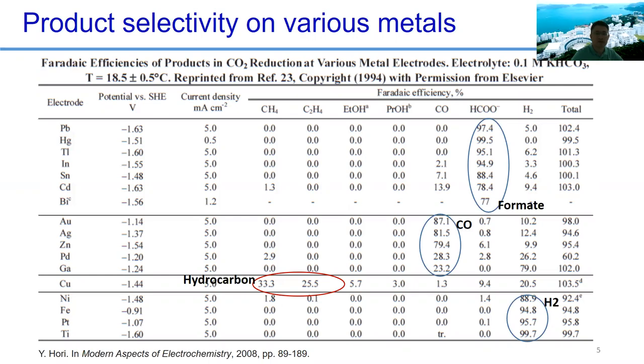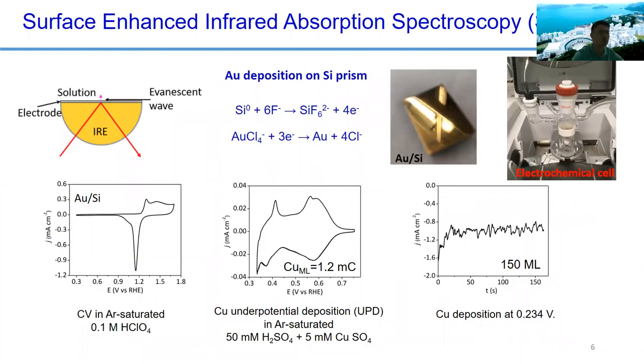And you can see that copper is very special. It's the only surface that can generate a large amount of methane and ethylene. Okay, so copper has been intensively studied in the past to understand why copper is so special. So we also try to do something to understand this carbon dioxide reduction process on a copper surface.